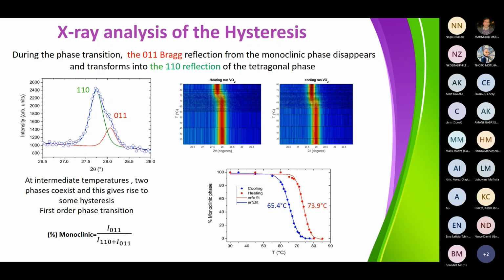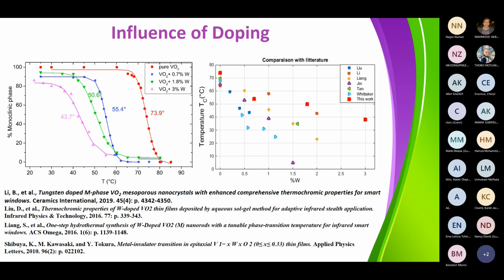So there is a hysteresis that you can find in the diffraction experiments, but you can see this also if you measure the resistivity of the films. You will also find a hysteresis. And you do that for different concentrations of tungsten.